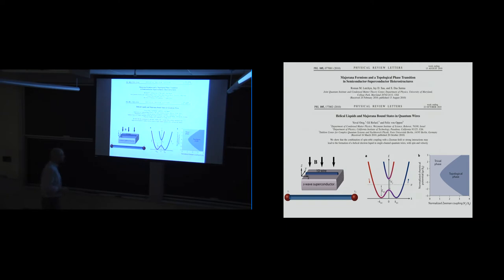recognize that the proximity effect could be effected by an S-wave superconductor. You know, tin, lead, aluminum, every superconductor you know, with a one-dimensional wire sitting on top of it, would work fine as long as the wire had sufficient spin-orbit coupling that the bands of the dispersion relation would be separated enough. And so here, drawn in this illustration, is the resulting band when you add the three essential ingredients, namely superconductivity, a one-dimensional system with spin-orbit coupling, and an external magnetic field applied transverse to the direction of the effective spin-orbit field inside of the wire, results in a band structure that looks a little like this Volkswagen symbol, the VW.